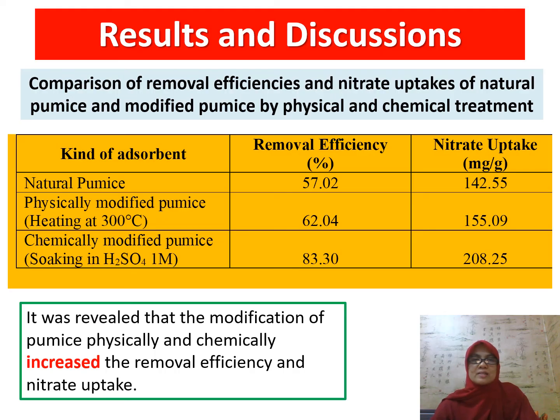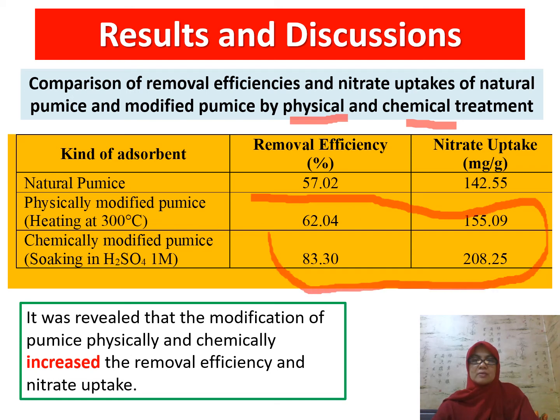This is a comparison of removal efficiencies and nitrate uptake of natural pumice and modified pumice by physical and chemical treatment. From this table, we can see that removal efficiency and nitrate uptake by using modified pumice are higher than by using natural pumice. It was revealed that the modification of pumice physically and chemically increased the removal efficiency and nitrate uptake.